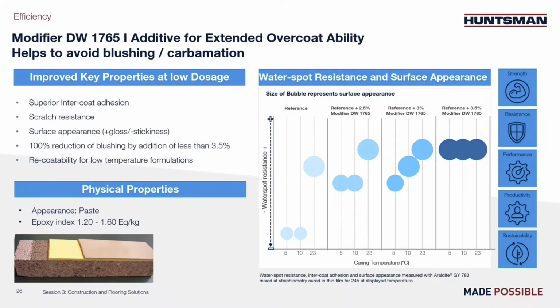Here, we wanted to speak about this product because one easy way to improve appearance or water spot resistance is to use an additive. And this additive is a modifier DW1765. It helps to reduce the surface defect. It also helps for intercoat adhesion when an additional layer is added on, and for scratch resistance eventually.